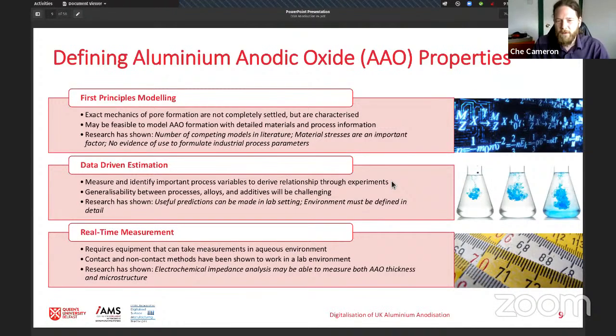So there's difficulties with data-driven estimation as well, which leaves you with the last option, in some respects, if you want to know what's happening: you can measure it. If you wanted to measure this as the oxide is forming, you need equipment that can take measurements in that aqueous environment inside the electrolyte. And again, in lab environments, we've seen contact and non-contact methods that have worked to measure the pore or the oxide layer thickness, and in some cases, some of the properties as well.